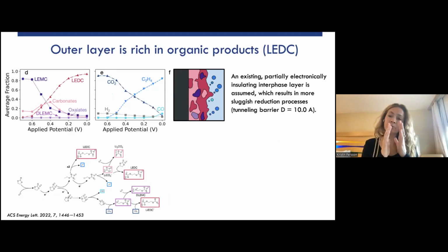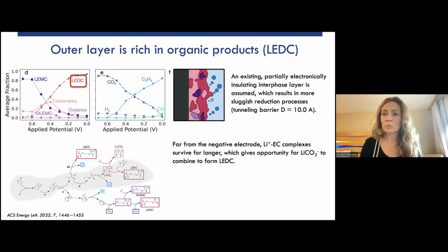As that film forms, and now we assume maybe that we have a 10 angstrom film, you are going to get a slowdown of the electrons. So an existing partially electronic insulating interface is now assumed. Further away from the negative electrode, your lithium coordinated EC complexes survive for longer, which gives an opportunity for lithium carbonate anions to combine through this path here and form LEDC, which wouldn't have happened earlier because they would have just reduced and formed lithium carbonate. That changes the competitive nature of these different reactions.